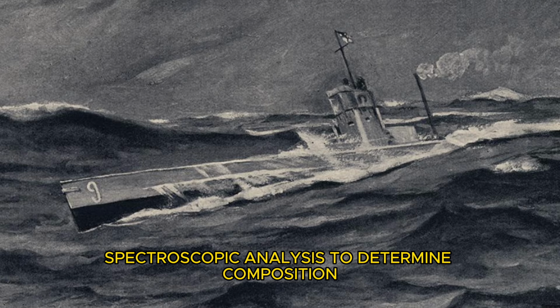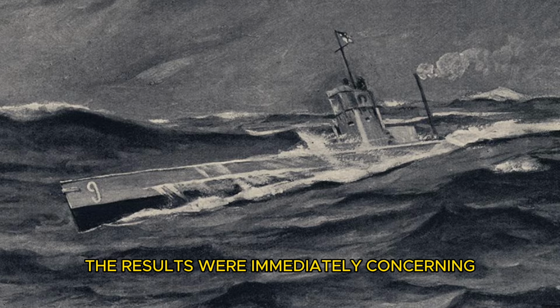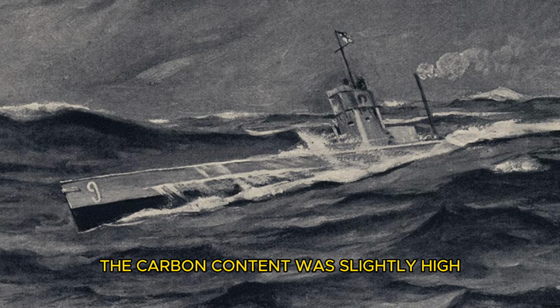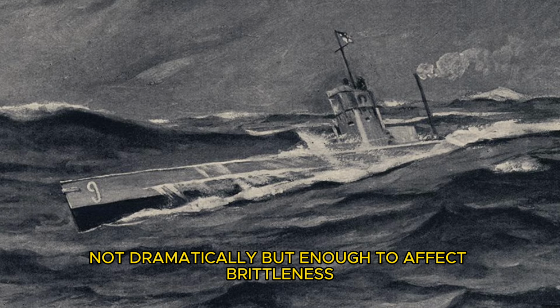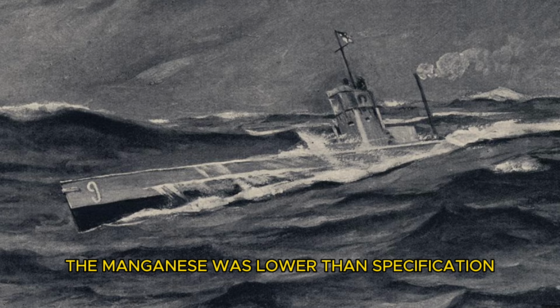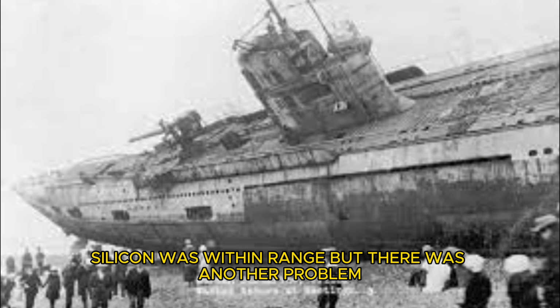Whitmore used spectroscopic analysis to determine composition. The results were immediately concerning. The carbon content was slightly high, not dramatically, but enough to affect brittleness. The manganese was lower than specification. Silicon was within range. But there was another problem. The steel contained almost no molybdenum.